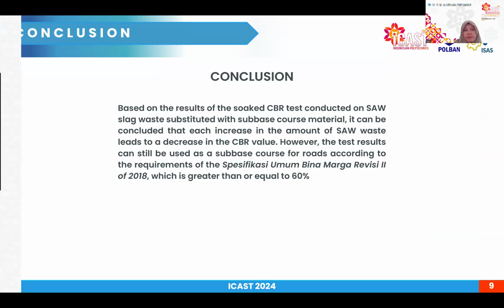Conclusion. Based on the results of the soaked CBR test conducted, where SAW slag was substituted with sub-base course material, it can be concluded that each increase in the amount of SAW slag leads to a decrease in the CBR value. However, the test results can still be used as a sub-base course for roads according to the requirements of the Spesifikasi Umum Bina Marga Revisi 2 of 2018, the Indonesian National Standard, which is greater than or equal to 60%.